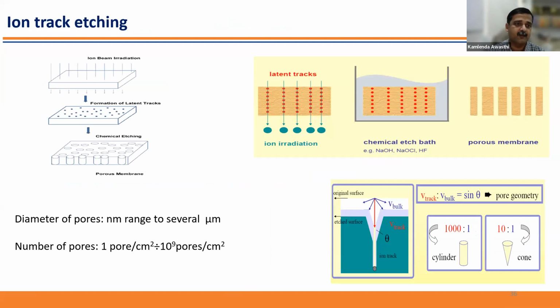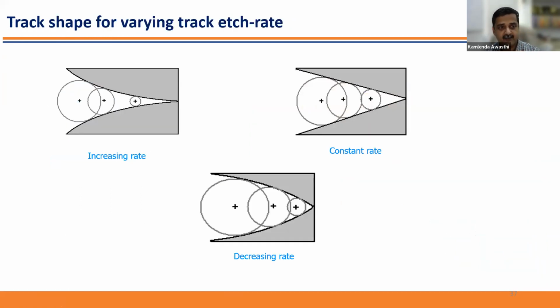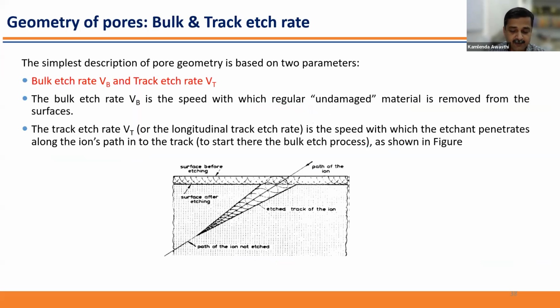And here you can see what is happening when this ion beam comes through your sample. This is the path of the ion beam, and later the damage that they have created can be removed chemically. So here you can get your porous membrane channels. But if you etch from one side and stop the other side, you can get the conical shape, not the cylindrical. So you can have various shapes and sizes by changing the parameters or the rate of chemical etching. So you can make different shapes in polymer nanofilters.